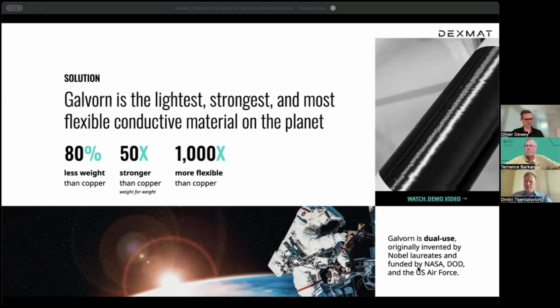Sure. I think this would need to be engineered or designed in the composite. So I think the questioner is right. If you make a composite in a standard way, you do a wet layup or something where the outside of the composite structure is essentially plastic, you're going to have that polymer inhibiting the electrical conductivity of the surface. With lightning strike protection, though, you're looking at extremely extreme electrical environments. So high temperatures, high voltages, lots of current. I don't know what would happen if lightning were to strike an outside plastic, inside carbon nanotube fiber panel. However, I would assume that at some point, very, very quickly, the polymer would cease to be a problem, and then the carbon nanotube interior would start taking over all of the conductivity.